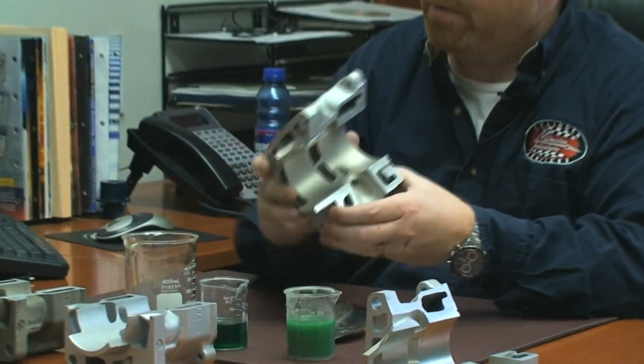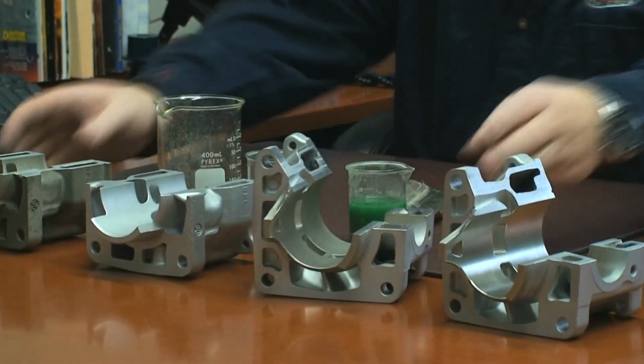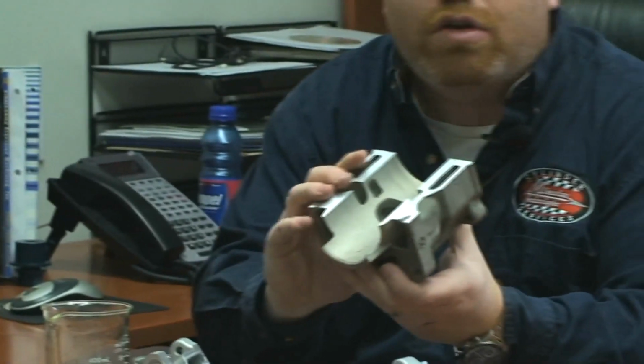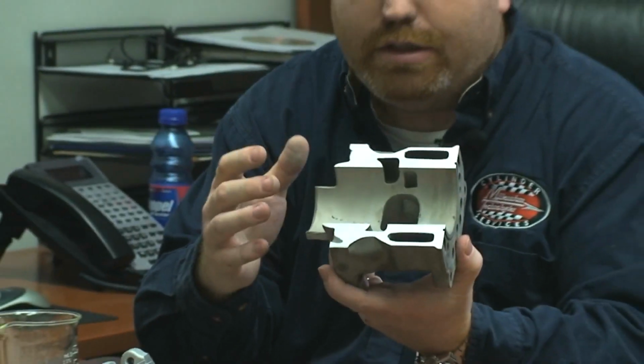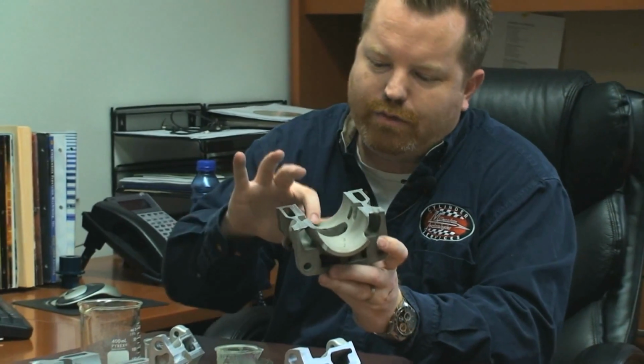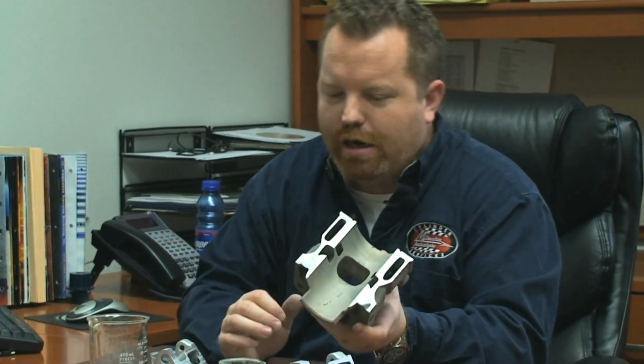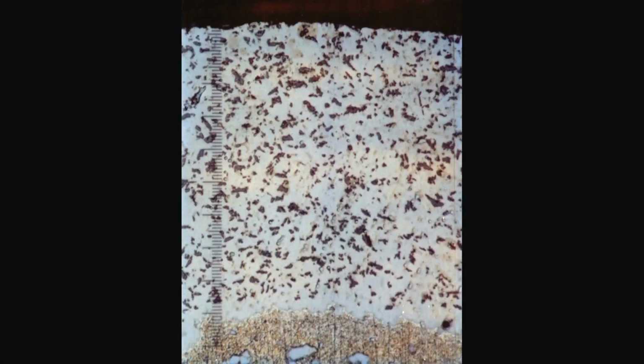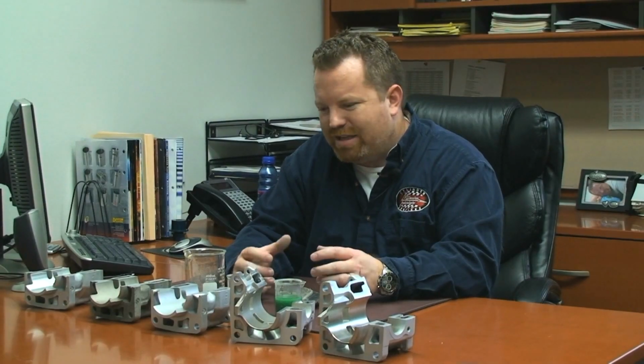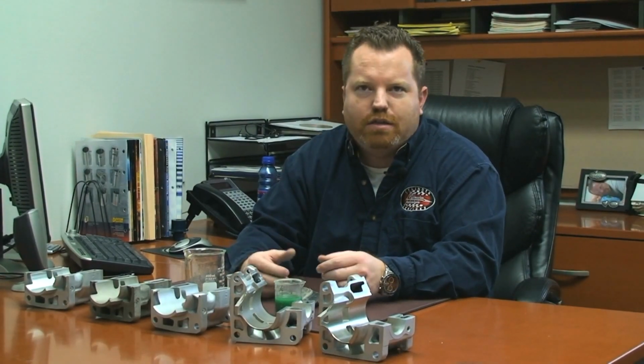This is actually cleaned up. A better example is this. This is what the cylinder looks like when it comes out of the plating tank, so you can see the coating as it looks here. In a magnified version, in this photomicrograph, you can see that the coating is a lot like cement, with the silicon carbide particles being the rocks in the cement, and the nickel being the mortar that holds everything together. So that's what the coating is and what it does.